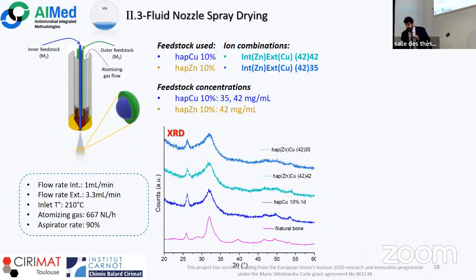So, we then tried to obtain at first a core-shell structure having zinc as the core of the particle and copper as the shell of the particle. And we tried 2 different combinations of the concentration in solid particles of the gels. One with the 2 gels at the same concentration, and another one with the core at a higher concentration.